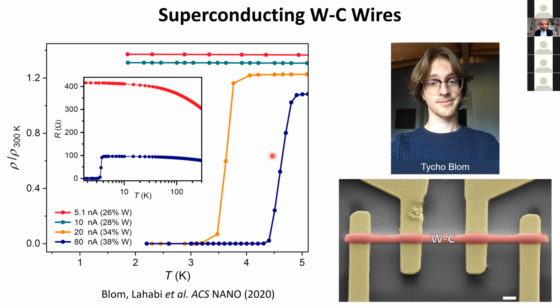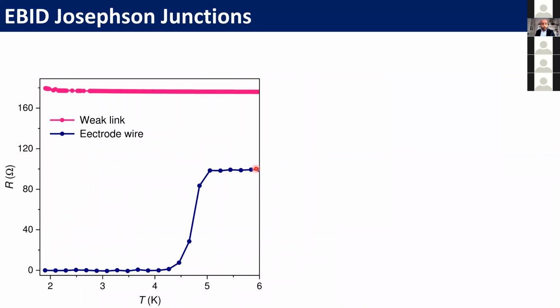But more importantly, we found that depending on how we scan the electron beam, we can make both superconducting and metallic but not superconducting components. And that provided us with the means to make our Josephson junction. So this is basically how we did it. If you scan your electron beam slowly, we found out we can make the electrode wires for our junctions, the superconducting components. But if we scan it fast, we can make non-superconducting components. And that is basically how we made our Josephson junctions.